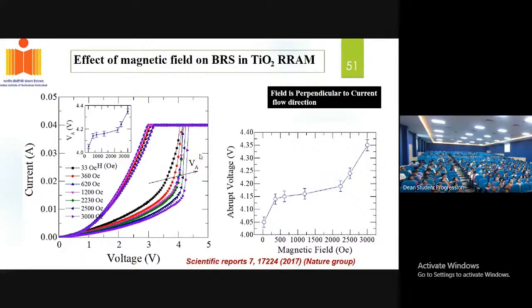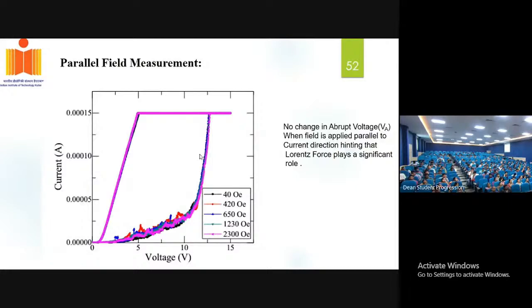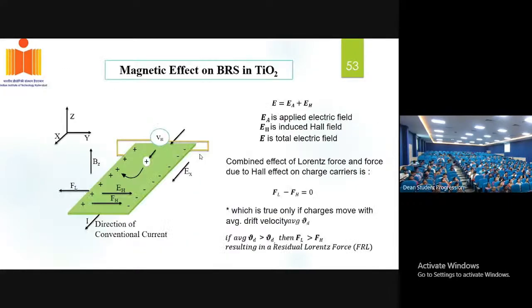When you apply the electric and magnetic fields perpendicular to each other, the device takes more amount of voltage to go from high resistance to the low resistance. On the other hand, in the parallel direction, we don't see any shift for the voltages. So this we could explain using the residual Lorentz force that exists in the device.